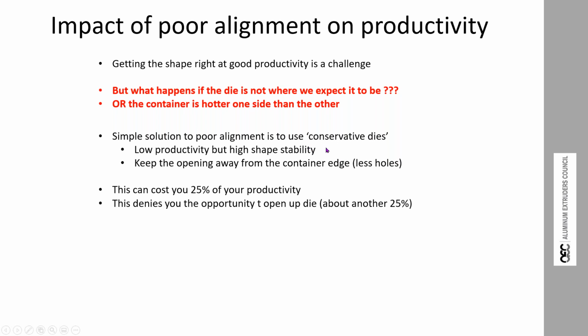And my experience hanging around extrusion plants for way too long is that the conservatism that is built into these dies, because of alignment and because of thermal saturation of the container, etc., can cost you at least 25% of your productivity. And I've had people look at me, BS. And we've got the press lined up and we've got things sorted out, and let's try running faster. And just doing a couple of simple things, not attending to everything, you've got 10-15% just there, sometimes more. The other problem is, not only is it holding you back from where you should be today, but it's also stopping you going where you could be tomorrow. You lose your opportunity to run more open dies, to open up the ports.